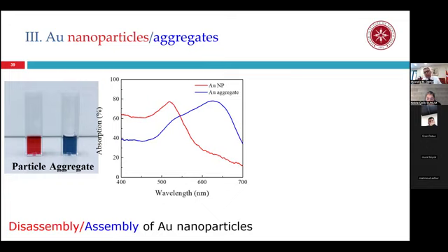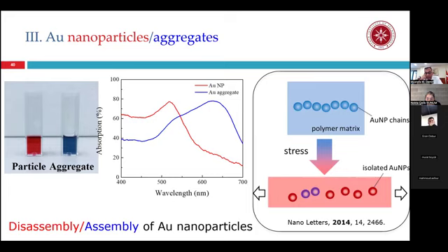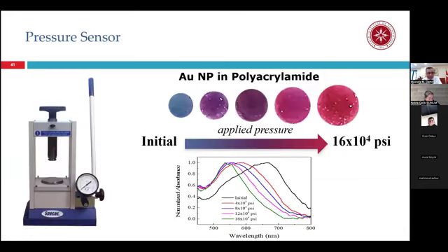Okay, this is surface plasmon. When the gold particles come together to form large crystals or aggregates, we see coupling of the plasmons, and the color changes from red to blue. And it is a very promising material for a pressure sensor. So imagine that you have blue colored aggregated gold particles in a polymer matrix. Then you apply stress, say pressure, and you somehow succeed to individualize the particles. The particles are individual after this application of mechanical stress, then it turns them red.